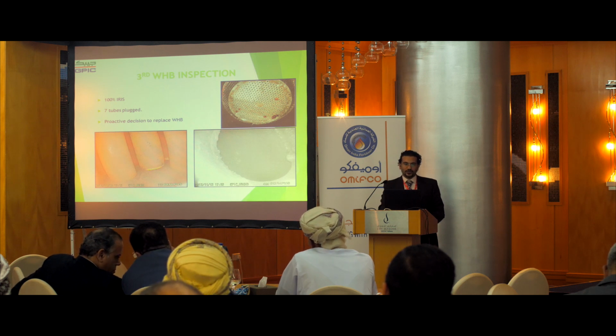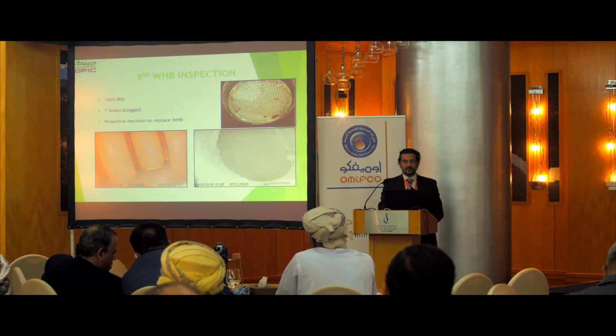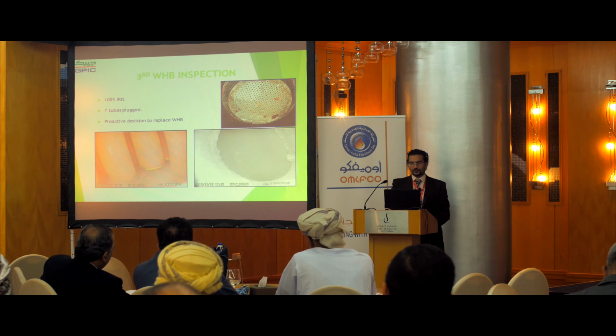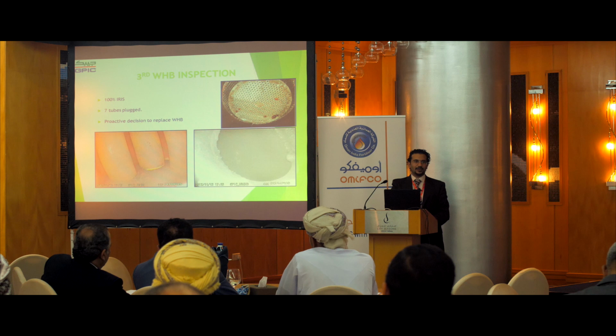And for our third waste heat boiler inspection, we did 100% IRIS on all the tubes. Seven tubes were plugged, not because of leaks, just due to thinning. And as I mentioned before, the proactive decision was to replace the waste heat boiler.